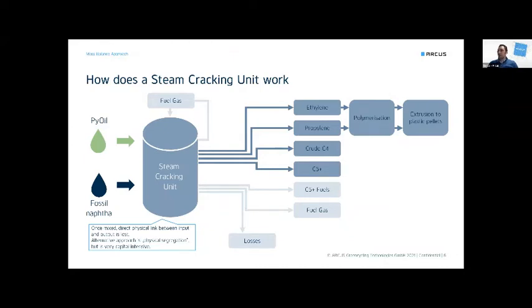I've already mentioned several times ethylene, propylene, C4, C5, but you also produce some pyrolysis gasoline, which is a C5+ fuel that cannot be used as a source for new polymers, some fuel gas, and of course, you always have some losses during a cracking process. Ethylene and propylene can be used for polymerization, going forward to extrusion and new plastics. So if you pyrolyze mixed plastic waste, mix with fossil naphtha, and go through a cracking process, you generate monomers which have the same specification as fossil monomers, and therefore you may produce virgin-like plastics out of waste.